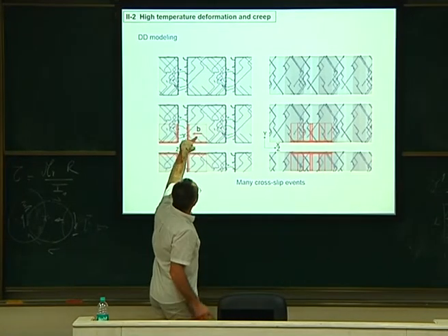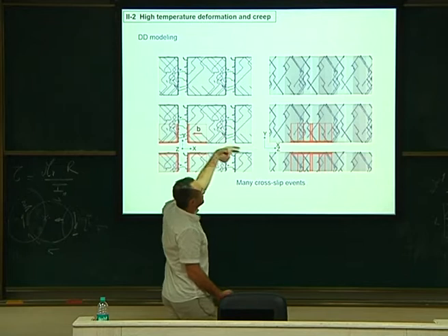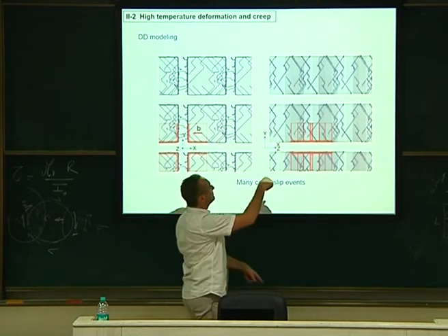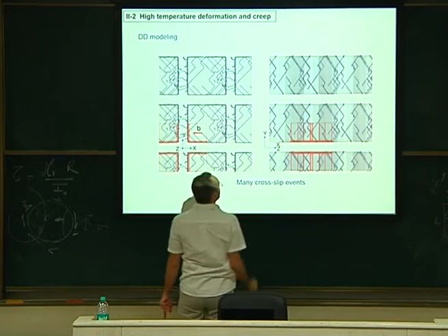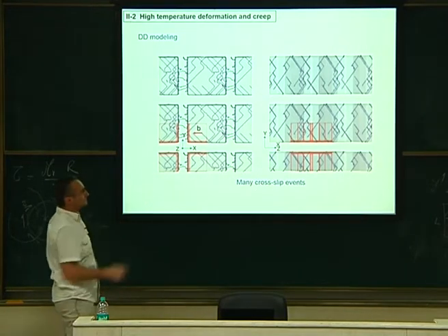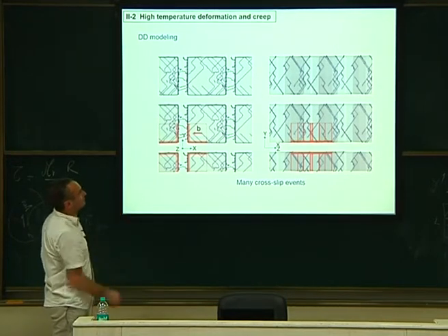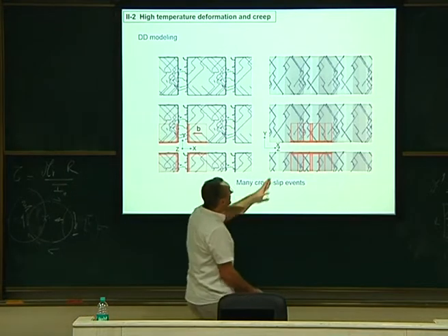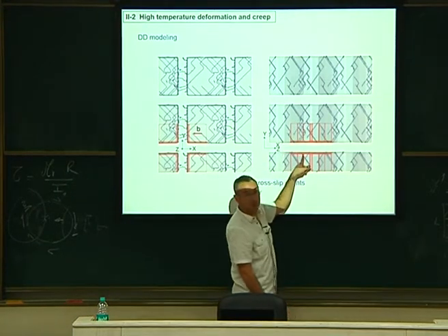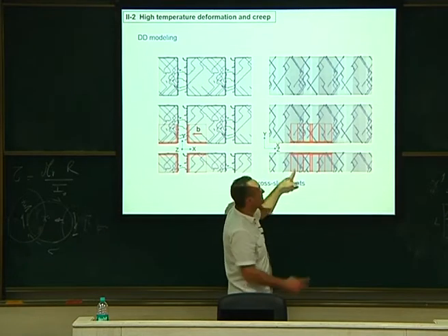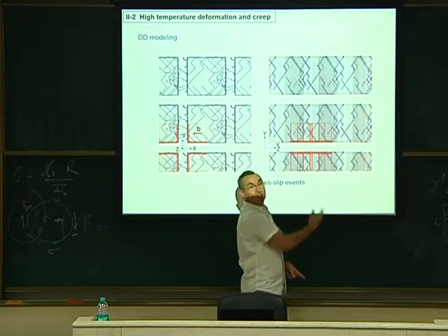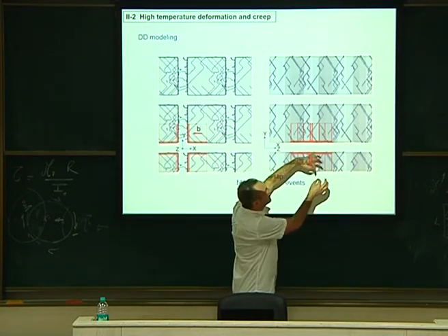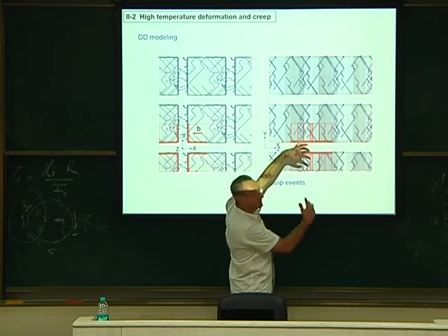If we look at the dislocation along the Burgers vector, if you look in that direction, here you can see the dislocation cross-slip planes. The Burgers vector is now on top of you. This is the 101 direction. And you see that it is a set of cross-slips at the interface of the gamma prime. And finally, the dislocation wants to align with the 0, 1, 0 direction. Because of the cross-slip, they want to be more or less vertical dislocation lines. So finally, if you have a large probability of cross-slip, you would get some straight lines like that, just by cross-slipping. Okay?